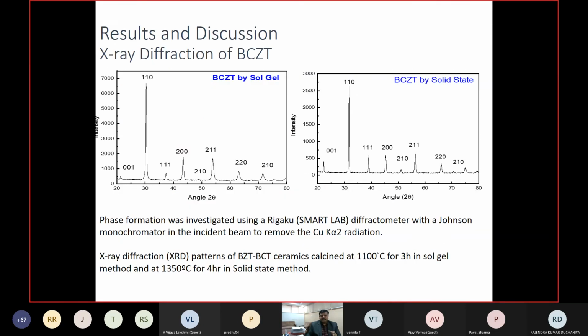So these are the XRD plots for BCZT. BCZT is BZT-BCT basically. She prepared the samples by two techniques, sol-gel and solid state. You can see in the case of the samples prepared by sol-gel, the peaks are a little bit broadened, which indicates the small particle size. But in the case of solid state, you can see the sharp peaks. That means the grain size is bigger.